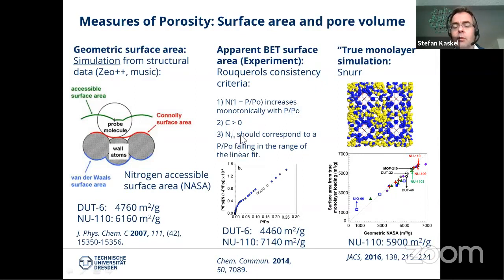So this value should not be seen as a geometric surface area. The geometric surface area can be calculated from the crystal structure. So we call this the nitrogen accessible surface area. And here you see a comparison. The BET is 7,000 square meters per gram. The NASA, the nitrogen accessible surface area from the geometric model, is only 6,000 square meters per gram. So there are huge discrepancies between these values.